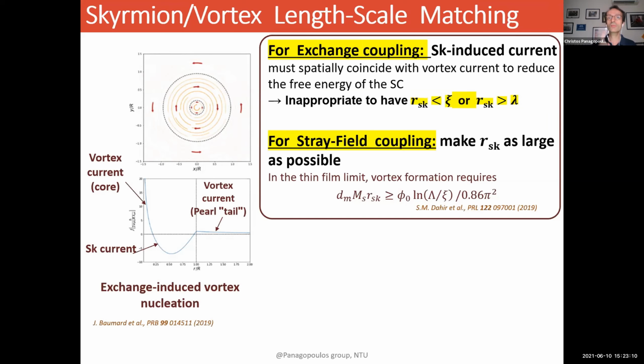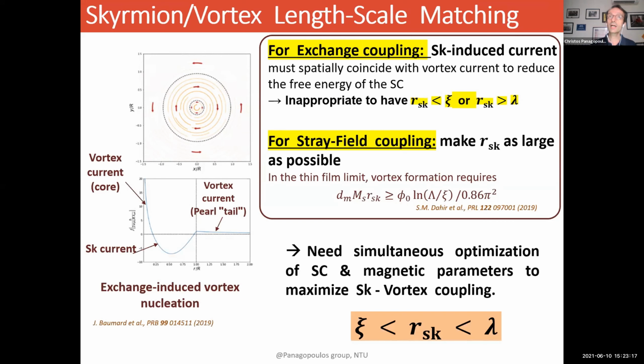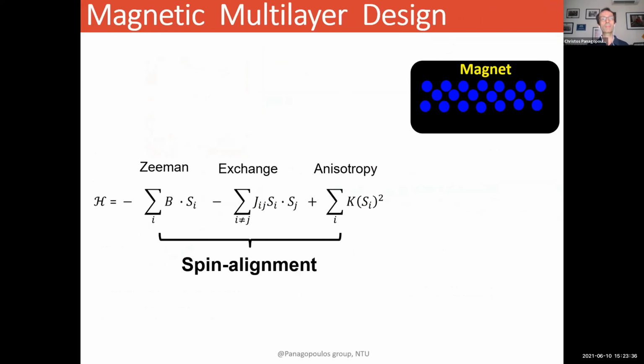So you need to satisfy these two coupling mechanisms by tuning the size of your skyrmion and the size of the magnetic penetration depth and the superconducting coherence length in your superconductor. So you need to devise a system where you can simultaneously optimize the superconducting and the magnetic parameters in order to maximize the skyrmion-vortex coupling between your superconductor and your ferromagnet. So the first task is to design the magnetic multilayer.